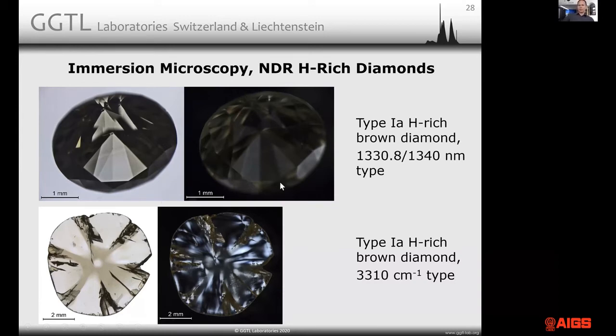And on the cross polarizing filters, you don't see any anomalous double refraction in such stones. So there is no strain. There is nothing. These stones don't lighten up. They don't get dark. They just stay dark like an isotropic stone is supposed to do. So that's the first type of hydrogen-rich diamonds.